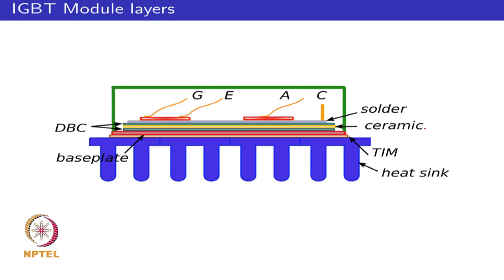Often you try to select materials for the ceramic and your base plate. For example, the ceramic might be aluminum oxide or aluminum nitride. Aluminum nitride has a better match of thermal expansion coefficient with your silicon, so it would be able to withstand more thermal cycling. Okay.